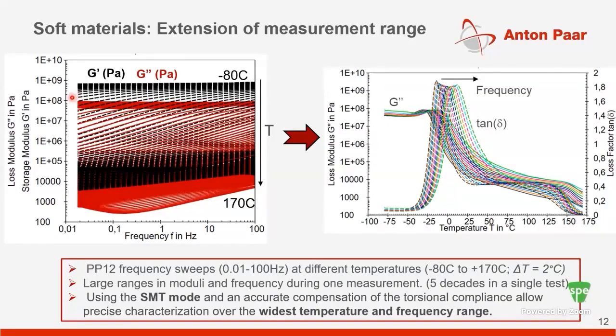At very low temperatures, characterization of the material is hard because the material is very stiff, so you need to exactly compensate for the torsional compliance in the system. At very high temperatures you need to worry about softening of the sample, and at high frequencies there could be inertial effects, which we saw earlier. So you need a controller which can control both these entities very well.